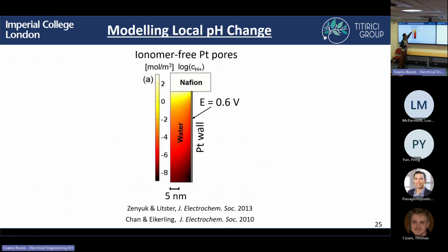And as you go from Nafion to a pore that's filled with water, so this is like a mesopore, like 10 nanometers wide, as you go from this proton-rich region into the pore, you obviously will then have this significant pH change within a pore. Now, this is just considering a single pore, not a whole catalyst layer. So we wanted to consider what's happening in the whole catalyst layer.